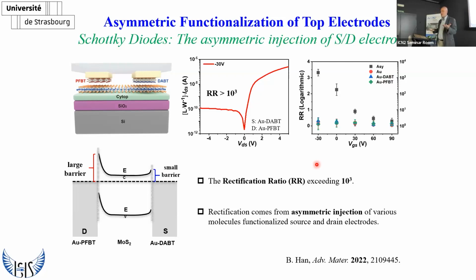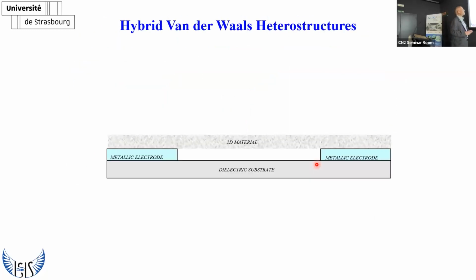Now, what is impressive about this story, and what we haven't yet published, is that you can do the same game also with molecules that are physisorbed. So they don't need to be chemisorbed and anchored very strongly. You can physisorb a thick, say 20 to 30 nanometer, layer of molecules, electron acceptor or electron donor, and again turn them upside down and put them at a distance. The statistic is about 20 nanometers, with some extremes of 7 nanometers. Now, I asked him if he could also put the electrode in a controlled manner on a single nanoribbon. He said the problem is not my hands, it's the optical microscope. Below 500 nanometers he cannot see. He claimed that if the ribbon is longer than 500, he has a 95% success rate, at least on its ends. Anyways, let's now pass to the van der Waals heterostructures.